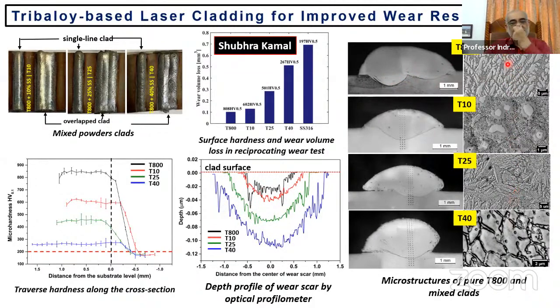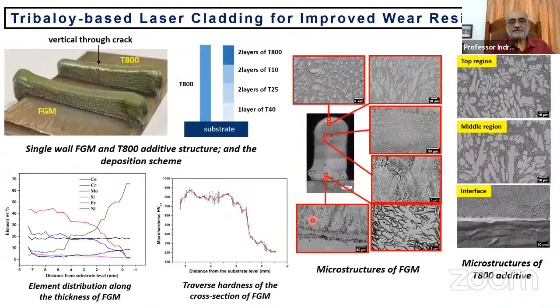So as you can see, this is primarily with plenty of intermetallic phases, including Laves phases. In fact, Tribaloy series actually has a good volume fraction of Laves phases. And this is how the micro hardness profile varies. And as you can see, with 800, you have the highest possible hardness, whereas in some other cases, you have lower hardnesses. And this is the clad surface, and this is how the wear track varies as a function of depth. So we can build such layers, and these could be functionally graded. So I can mix 10, 20, 50, 100% and change accordingly so that the compatibility is better.